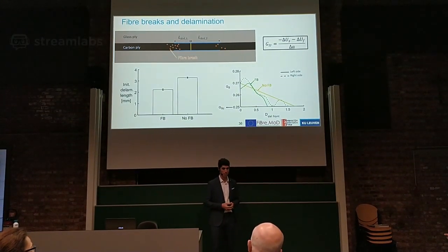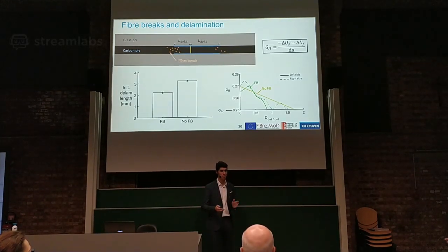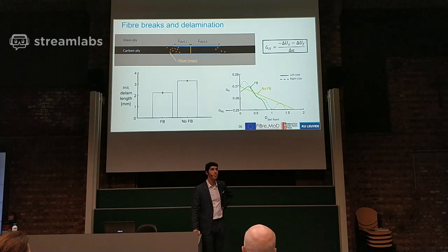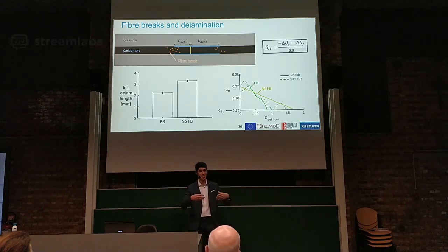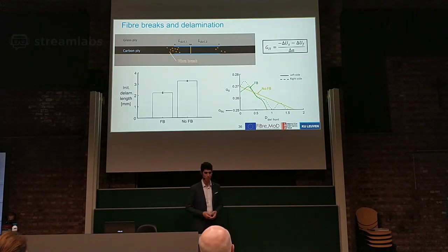Also, the way the fibers are non-linear in their behavior, something must be adapted to that as well. So, what do you think would change in the cluster formation, for example? Good question. So, if the fibers' stress concentration changes, how would they change? So probably they would extend a bit the region where the stress concentrations are applied, because as we've seen with the matrix, if we have more plasticity, then this region of stress concentration increases. So probably these clusters would perhaps be a bit more dispersed versus the coplanar, if you agree with that.